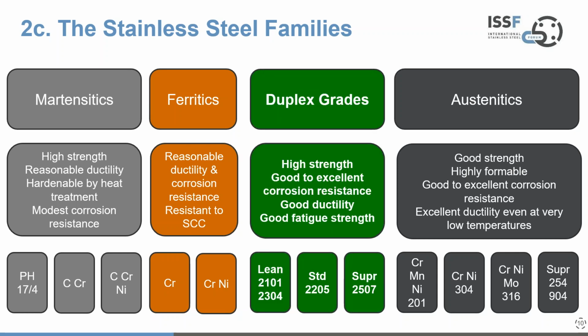Now, sitting in the middle is the new kid on the block, so to speak, the duplex family of grades. And when I say new kid on the block, these grades have still been around for about 80 years, so they're not that new in the scheme of things. But this is a combination of austenitic and ferritic structures in the same material. And what this brings together is the strengths of both of these types of stainless steel. So you have very high strength, good as a minimum to excellent corrosion resistance, good ductility, good fatigue strength.